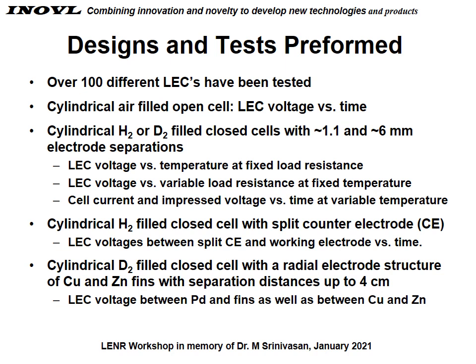and cylindrical deuterium-filled closed cell with radial electrode structure of copper and zinc fins with a separation distance up to about 4 centimeters. I'll say something more about this and show some figures here, but basically what we were trying to do here was do the contact potential difference measurements if we were ionizing the gas, and we could measure LEC voltage between the fins.